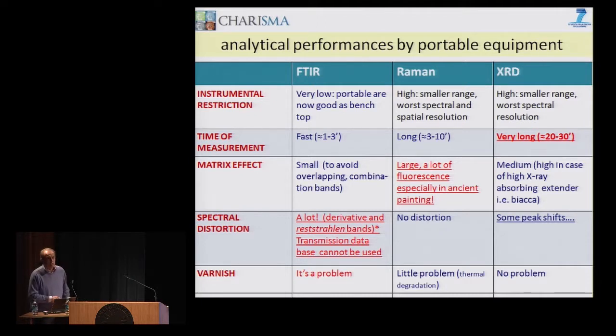And talking about spectral distortion, here infrared is terrible, because there is a lot of distortion due to the fact that you have two reflections, the specular and the diffuse reflection. According to the different roughness, you have different percentages of the two, and a lot of distortion appears in the spectra that you obtain, and the transmission data that are normally used to interpret infrared spectra can't be used. Raman shows no distortion, and XRD shows some shift in the peaks, which in any case can be controlled. And varnish is again another problem for FTIR, while it's not a big problem for the other techniques.